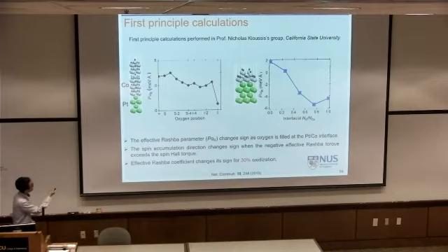When we put the oxygen all the way at the top, corresponding to away from the interface, and we gradually move oxygen in this way, there is some modulation in terms of intensity. But as soon as we put the oxygen at this very first interface, then suddenly the sign changes to a negative value. So this calculation indeed indicates this interface is very important to change the sign.